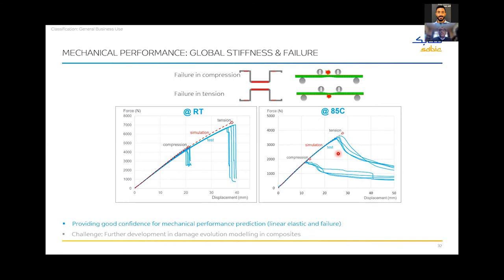And this was the onset of our work with GEELS for the last 3 to 4 year program. We realized we had a gap, and this gap had to be addressed because there's a lot of energy that we're not capturing through CAE here. So we wanted to close that gap, and that's what we worked on. So it's still a challenge. I'll leave GEELS to comment if he agrees or disagrees. I think it's still a challenge to get all of this addressed, but we're making tremendous progress to build that confidence in the industry that these things do work at the end.